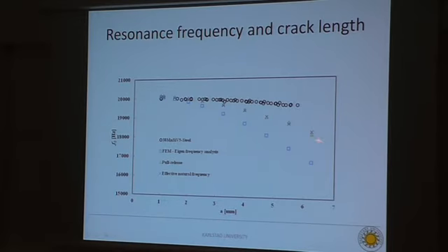But still, there is something missing to the experimental results. So we needed to do something else. And we started to think of the idea that these frequencies are actually not the frequency of the specimen, but rather the frequencies of the whole system, including the oscillator and the horn.